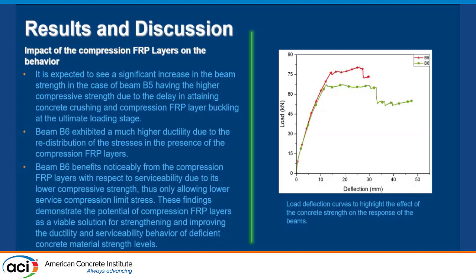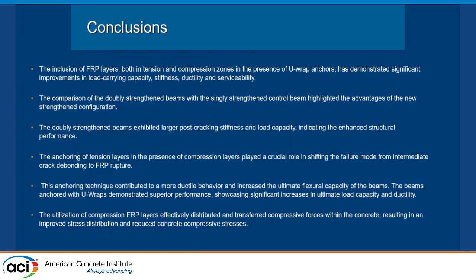It's expected to see a significant increase in the beam strength in the case of beam B5, having the higher compressive strength, due to the delay in attaining the concrete crushing and compression FRP layer buckling. Beam 6 exhibited a much higher ductility due to the redistribution of the stresses in the presence of the compression FRP layers, and beam 6 benefited noticeably from the compression FRP with respect to serviceability due to its lower compressive strength, because we have lower compressive strength and we were able to increase the ductility by adding the compression sheet.